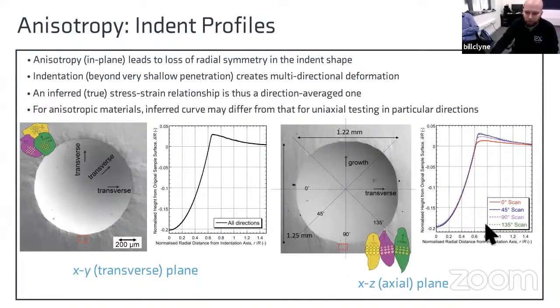And that is because of the different pileup we can see on the right-hand side that occurs in the different directions. So in the transverse direction, indicated on the graph as the 0 degree scan, we have less pileup. And in the 90 degree scan, so in the growth direction, we have much more pileup. That indicates to us that in the transverse direction, the material is more resistant to plastic deformation, i.e. it is harder, which is the same as what we saw in the nominal stress strain plots previously.